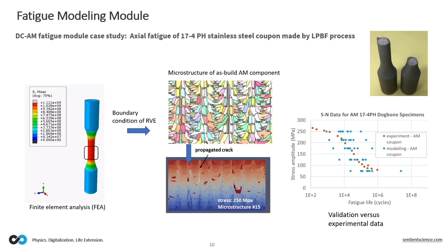And then the best case scenario is that either you have a very clean microstructure or the void that you have is not in a critical location. So we are predicting that range to make sure that we consider all the possible scenarios. And then, of course, as you can see, experimental data are right in the middle of that behavior.